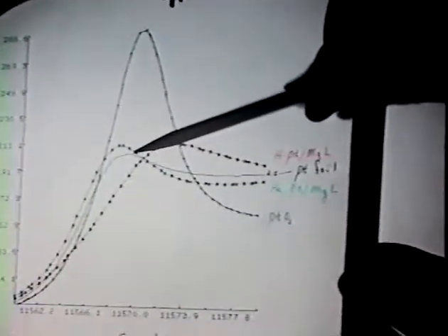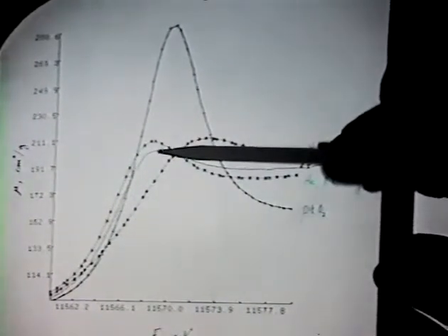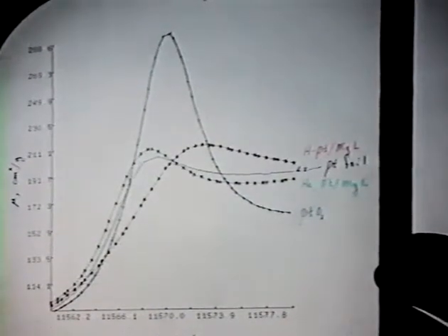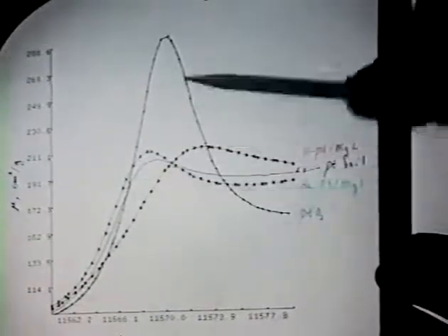And the way I'm going to do it is, because they're rather subtle effects, I'm going to take a sample of the catalyst, line up the inflection point, and subtract platinum from it, and only look at the difference spectrum. Right at the inflection point will be changes right at the Fermi level, and anything that happens elsewhere will be deeper down.